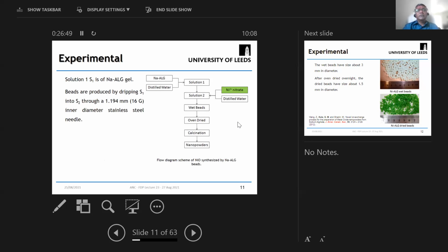So solution 1 is the sodium alginate solution. Solution 2 is a nickel nitrate solution. We made the sodium alginate solution and squeezed the drops of sodium alginate into nickel nitrate solution. And instantaneously the beads are formed; they retain the shape from the runny gel, which is sodium alginate. When you squeeze out the beads into nickel nitrate solution, it retains the shape in the form of wet beads. And then these wet beads are sieved through appropriate sieves, and oven dried and calcined to produce nanoparticles or nanopowders.